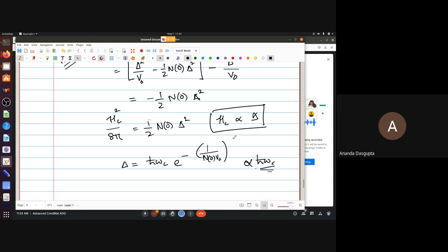Now, if superconductivity had been a purely electronic phenomenon, replacing the nucleus by another heavier nucleus would not have any effect. We would not expect changing one isotope for another to produce a big difference, because the electrons are the same for two isotopes and they are in the same configuration. Having a heavier isotope simply means that the nuclei take more time to move around, but that should not really affect the electronic behavior.